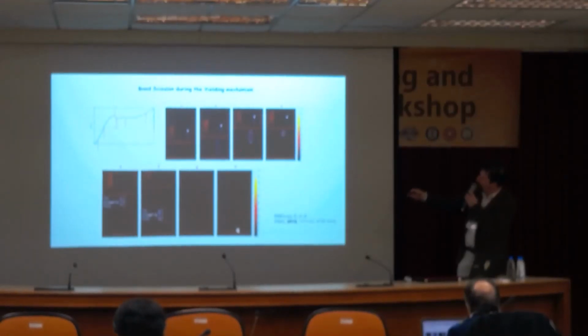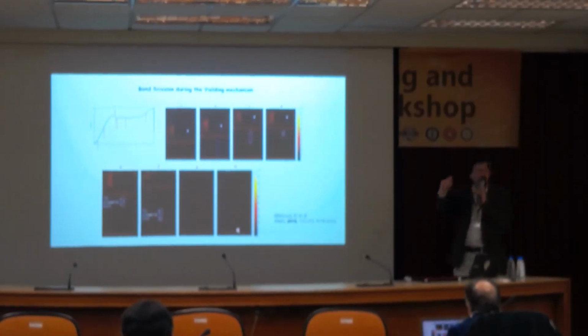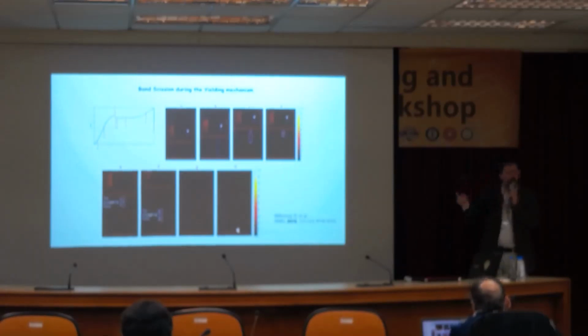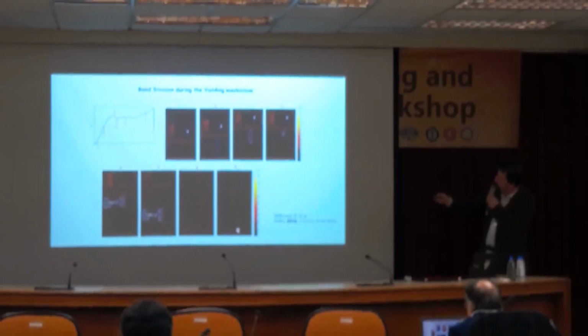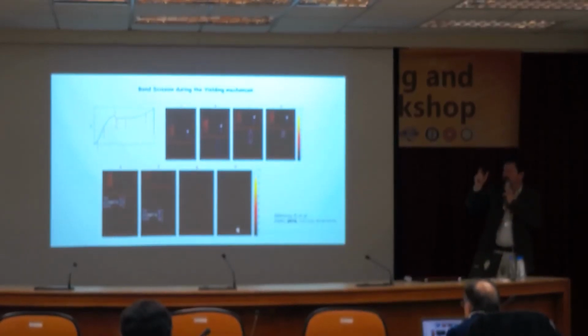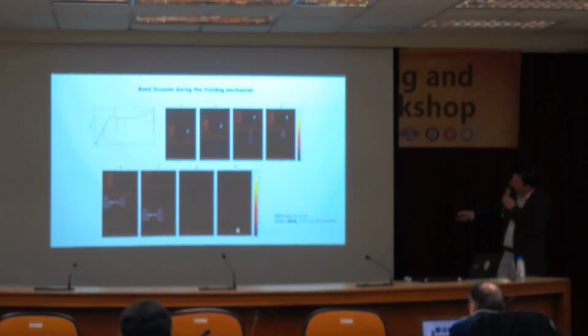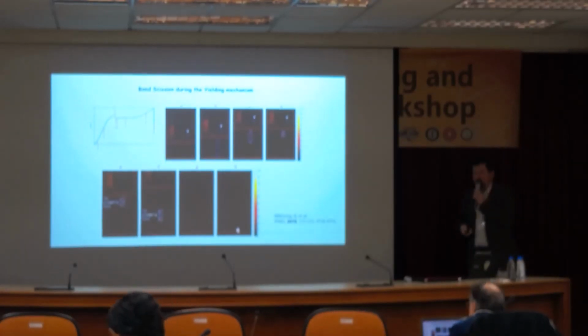You've observed the sample, and you see actually initially homogeneous light emission above this point here, number 2, that shows us that we are breaking bonds inside the material, but randomly, and not in a localized way. As soon as we get here to this point, we start breaking non-randomly, and we have localization of bonds at the point where you go from the less stretched to the highly stretched. And we can actually quantify that. We see here a localization, then it moves, and we see the necking exactly as in the real-time experiment. So we can actually quantify the breakage.